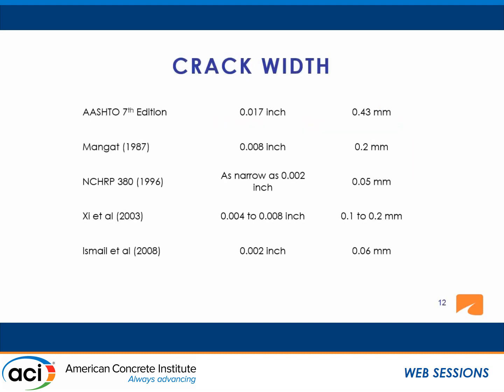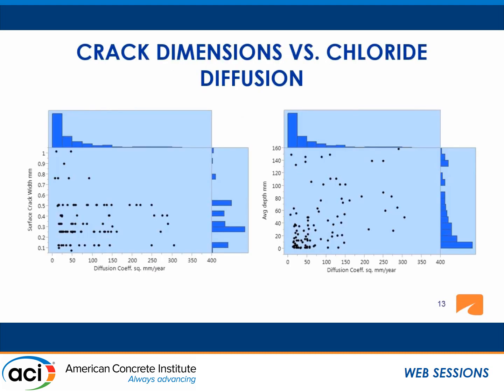And we wanted to see how the dimensions of the cracks themselves would play a part in causing the significant increase in the chloride diffusion. And we went through the literature, and there are numerous studies which attempt to assign a threshold crack width above which significantly higher corrosion would be expected. And these are our results.